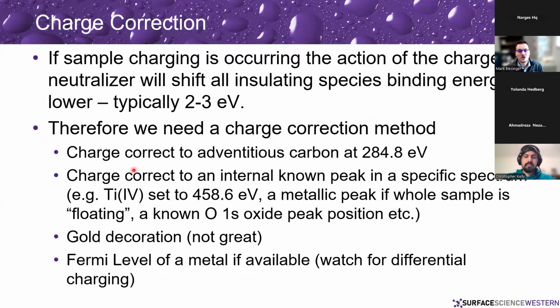There are a number of things that you can do. You can charge correct to adventitious carbon at 284.8 eV, and that's the aliphatic line of the adventitious carbon, not the peak maximum. You have to find out where the aliphatic line is because that's what we're correcting to. If it's an organic material, not adventitious carbon, you need to figure out, okay, what is my aliphatic peak or something in reference to that? If you have graphite present, that's a different charge correction. It's not the same material. So charge correcting to a graphitic peak is doable as well. We do it here, but it's not at 284.8 anymore, it's 284.5.